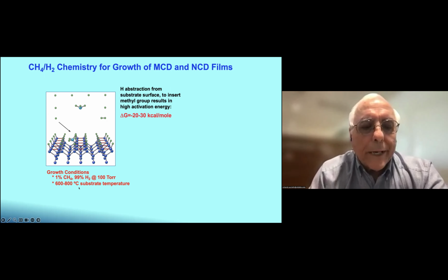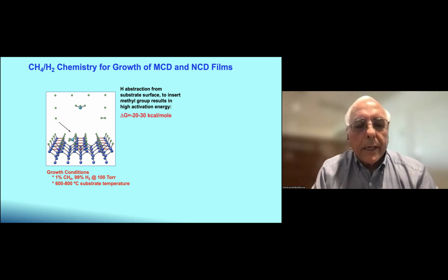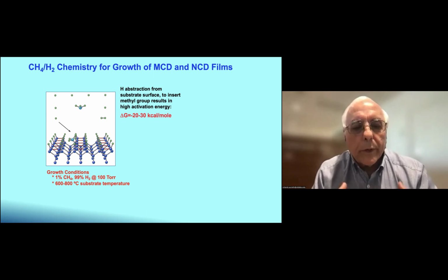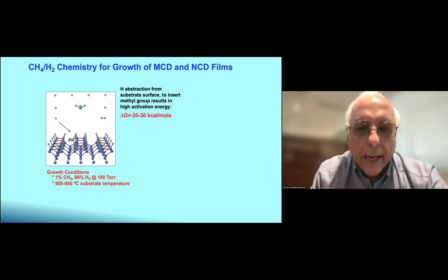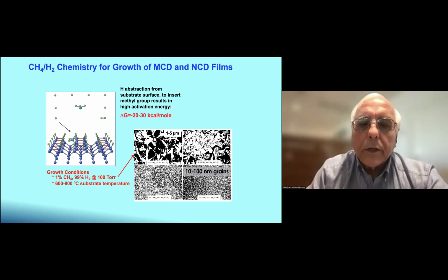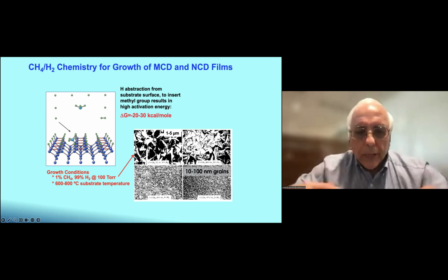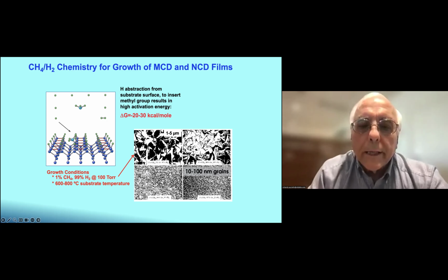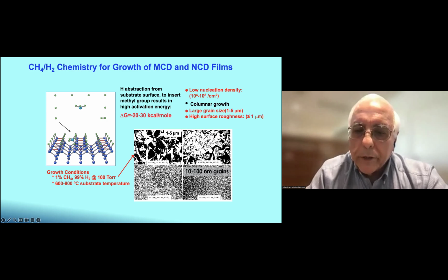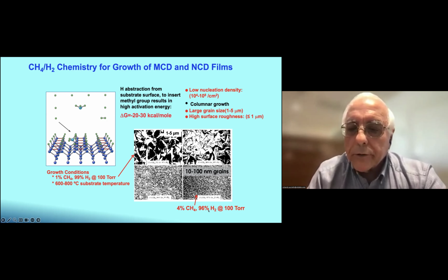And the reason they put so much hydrogen is because they observed a graphitic phase being co-deposited, and atomic hydrogen produced in the plasma etches the graphitic phase easier than diamond. But what they didn't realize is that the small nanocrystalline diamond grains that we're trying to renucleate were also etched by that. And in the end, they were only able to grow microcrystalline diamond due to the coalescence of the nanograins that couldn't survive.